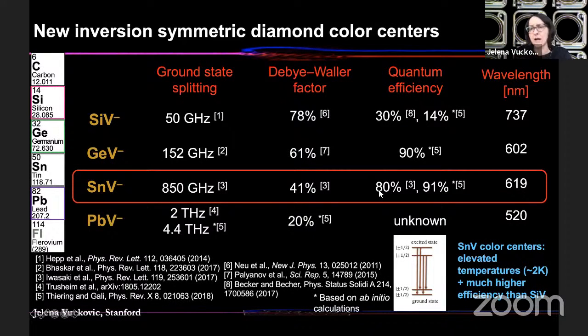And also the internal quantum efficiency of tin vacancies is significantly larger than for silicon vacancy, which makes the atom brighter. And that's also, of course, preferable. But other than that, the energy level structure is exactly the same. The wavelength is different. You have to operate at a little bit shorter wavelengths. So you need a new experiment, a new set of lasers, like in AMO, whenever you switch an atom, but everything else is exactly the same. So that's what we work on.